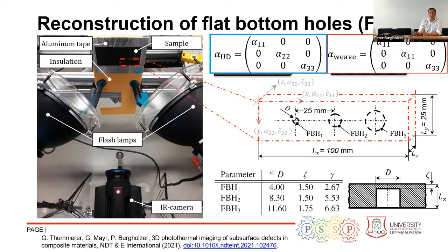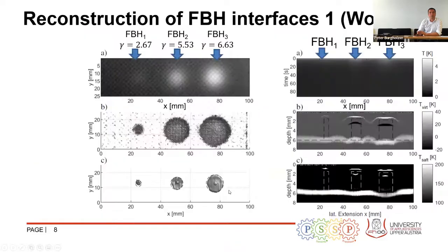The diameters go from 4 millimeters up to nearly 12 millimeters. We have different depths and different ratios of the diameter to the depth. And now we try to reconstruct the position and the depth of these flat bottom holes. And you can see here the results.